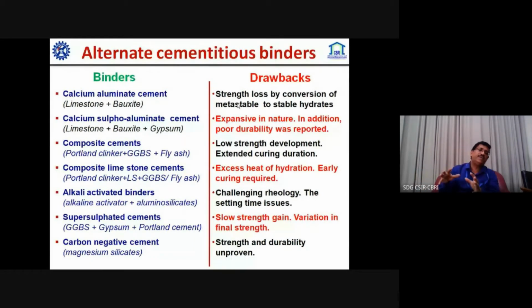But if we are having good quality production, that will be minimized. So if we talk about calcium aluminate cement, it is basically limestone and bauxite, and very limited calcined requirement is there. So energy consumption will reduce, and CO2 emissions will also reduce by more than 30%. But sometimes people have observed, not all, that there was strength loss by conversion of metastable to stable hydrate. So during reactions, some strength losses they have observed.